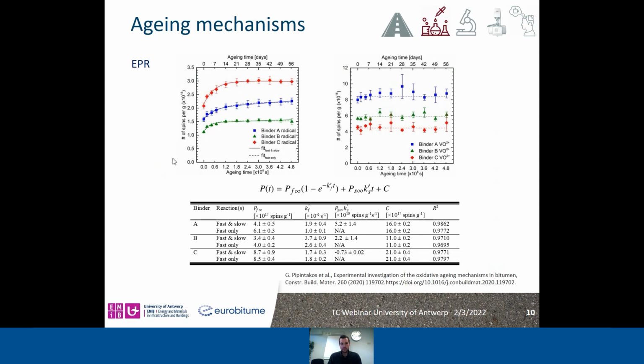And the interpretation of this for the organic carbon-centered radicals is based on the fact that oxygen-centered radicals, which according to previous hypotheses for the chemical paths are produced, yield carbon-centered radicals during the fast rate phase, and afterwards during the slow rate phase, the rate of production and formation most probably is equal, and for that reason we observe a plateau in all the binders, independent of the binder type, source or distillation.